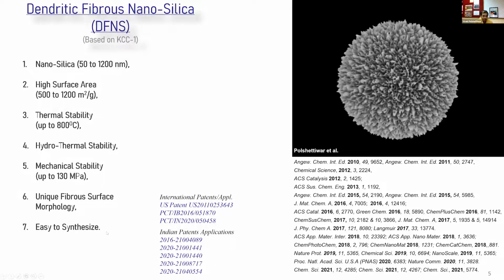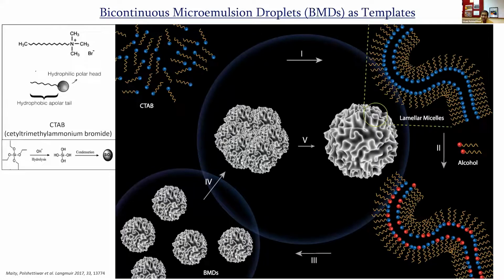Before I explain the catalysis part, I also want to explain in brief how we synthesize these materials, the formation mechanism of dendritic fibrous nanosilica. This is a templated synthesis. We use CTAB as a template molecule, a surfactant, and we know that whenever we add a surfactant into a solvent, they try to form micelles, normal or reverse, or if the concentration is higher, they also form lamellar micelles. So I will show you the animation.